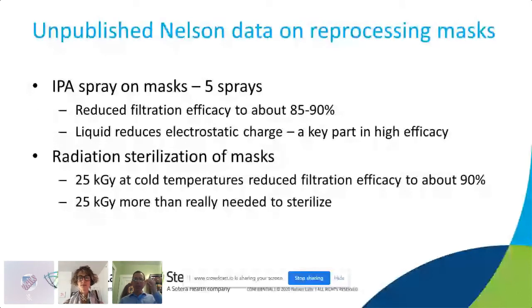So just a little bit of data I thought I'd provide that we've gathered over the last little bit on reprocessing masks. We've done some testing with IPA sprays. The IPA has been very effective, of course, at killing vegetative microorganisms. And we found that it reduced the efficacy of an N95 to about 85 to 90%. So instead of 95, they went down 5 or 10%. Now, that was a single use, a single reprocess. But that was fairly well soaked. That mask material was soaked after those sprays.